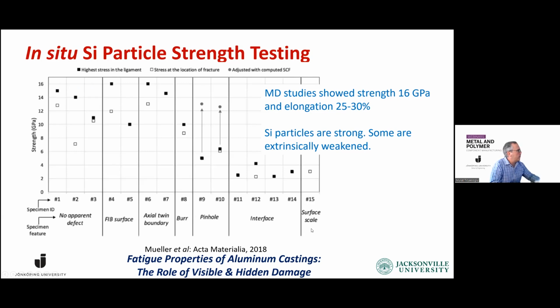And what they found is the maximum strength they recorded is about 16 gigapascal, which corresponds perfectly with the molecular dynamic studies, which reported 16 gigapascal and about 30% elongation.